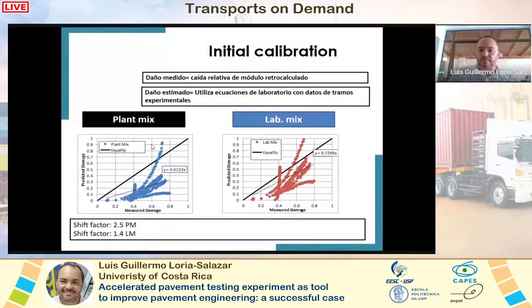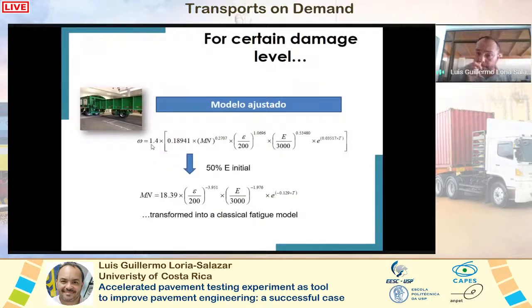With that, we do a calibration for the plant mix and the lab mix, and we realized that the shift factor for the plant mix was 2.5 times, and the shift factor for the lab mix for fatigue was 1.4 times. So basically, accounting for the damage, taking 50% of the initial moduli, we transform our data into a normal fatigue model like the one you are seeing in the slide. So the number of loading repetitions, in millions, is equal to this equation that we have, related to the strain, to the stiffness, and also to the test temperature, that we found highly significant for our experiment.